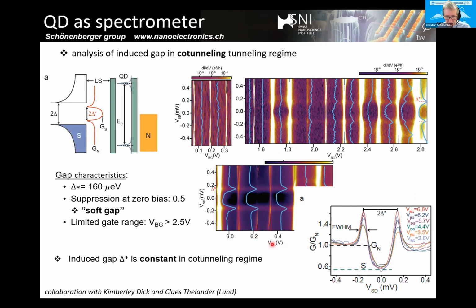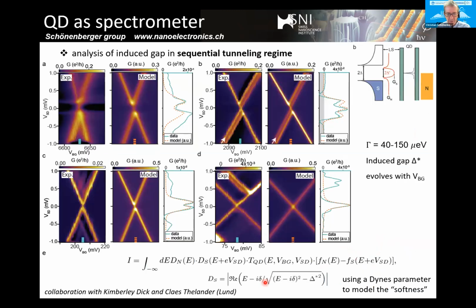And if you go to large voltage like 6, then it's a nice gap, which has the right size, of the order of 150 micro eV. And if you now plot this, as one should do, the conductance against the normal state conductance, then you see there is some suppression, but the suppression is very weak. It's a factor of 2 suppression. We should call this a soft gap, and the softness doesn't change much with the gate voltage. So here we have a soft gap, and here will also be the question, why is it soft?